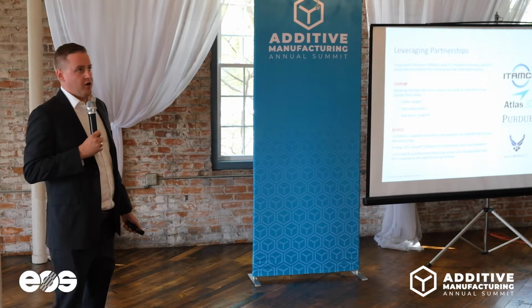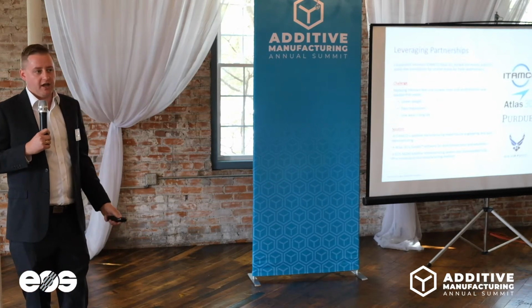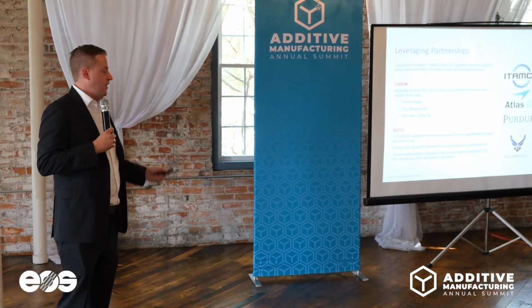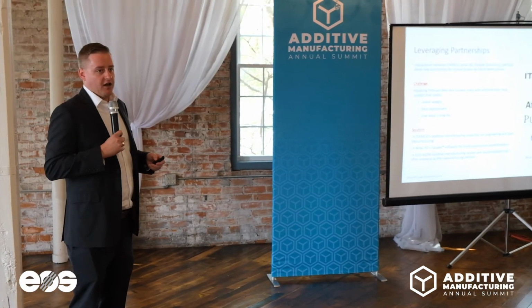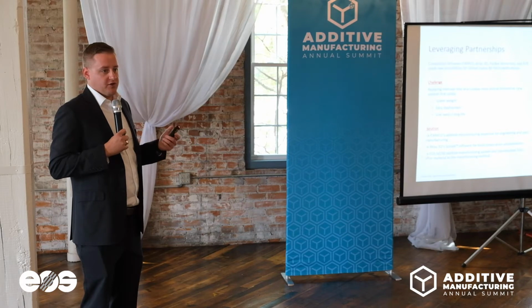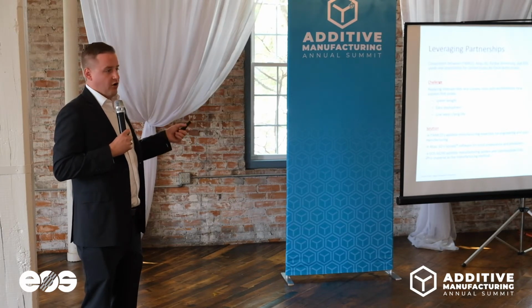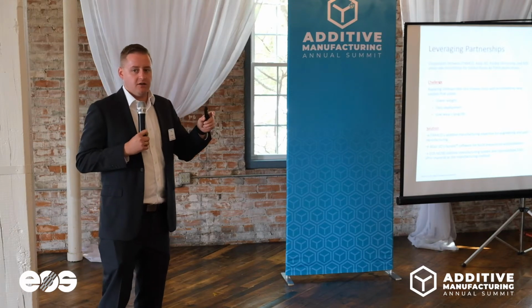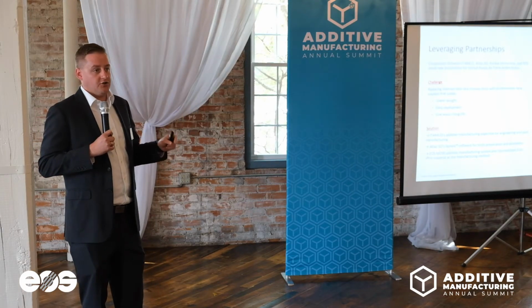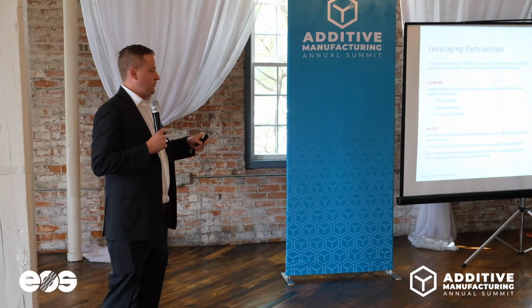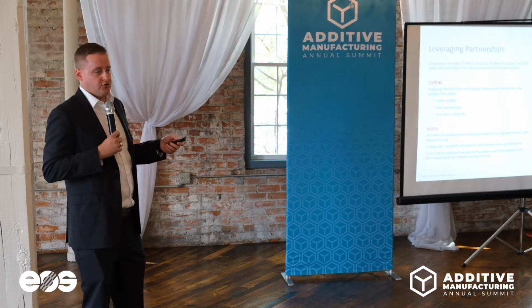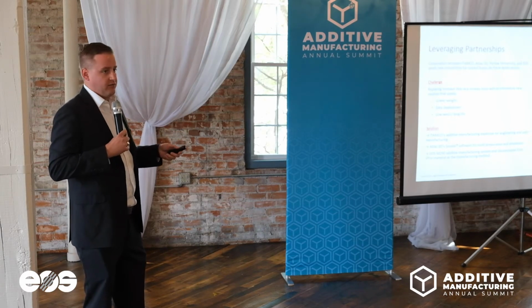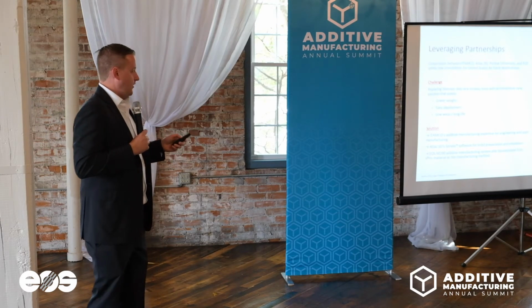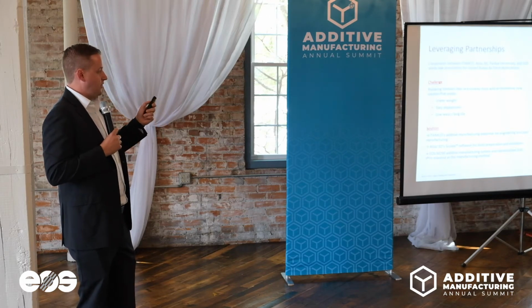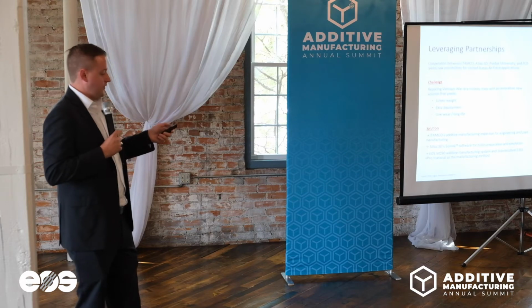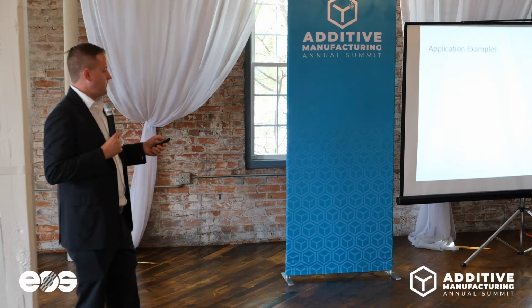Traditionally, a lot of the metal powders are atomized using a gas or plasma atomization process. This is a water atomized 316L, has a much wider powder particle size distribution, which makes the powder a lot cheaper. But we're also going to sacrifice a few percentages in density to drastically decrease the build time. So something that would typically take, say, 20 hours to produce using this new powder process, it may take 10 or less hours. And this was a joint project between ITAMCO, Atlas, Purdue, and ultimately delivering components to the U.S. Air Force.